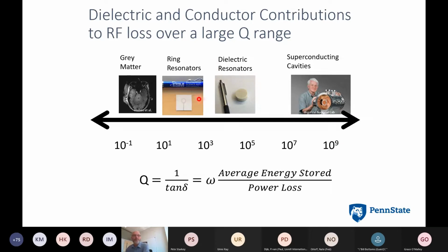And then, of course, we talked about the ring resonators quite a bit. Permittivity values are around 10 for the substrate, but more importantly, the Q value for the resonator is in the 100 range, right? And then I also work on magnetic resonance imaging, and there we're looking at resonators for enhanced MRI signals. That would be a separate presentation. But what I find fascinating is the Q values we're competing with are 1. Here, because the body is so lossy, the Q value is actually around 1 for the body,